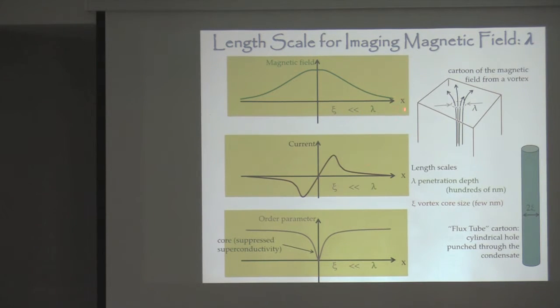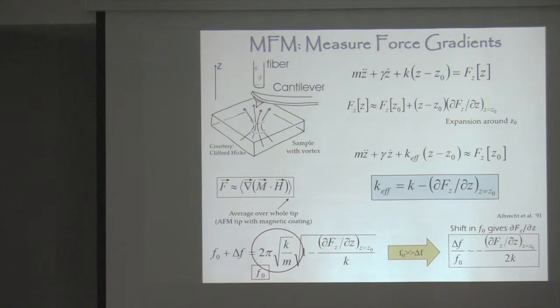Okay, so the tool that we use to get to this sub-micron scale, where lambda is a few hundreds of nanometers, is magnetic force microscopy, and it's a very simple technique. It's closely related to atomic force microscopy. We have a sharp magnetic tip. We bring it to a sample and it interacts with the sample, and so a force acts on this sharp tip, and then because of this force, the cantilever that holds the tip is going to bend. Okay, and then you can measure how this cantilever bends, and this is our signal.